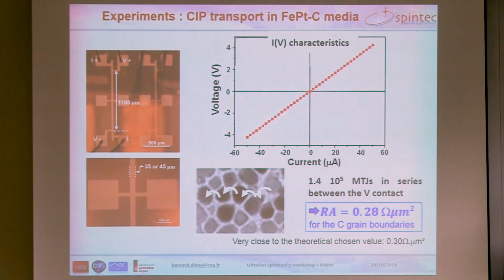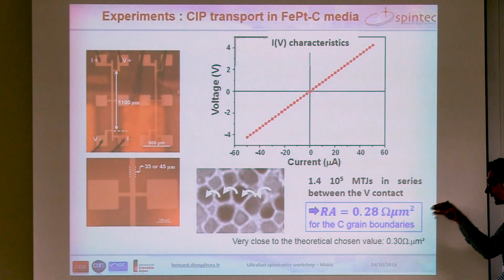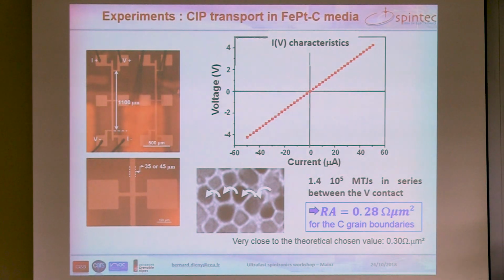And so in terms of electrical transport, the electrons are flowing in the plane of the recording layer. And basically, they are tunneling from one grain to the next through these carbon grain boundaries along the electrical field direction. So we can consider this recording medium as a number of tunnel junctions connected in series. And we have about 1.4 10 to exponent 5 magnetic tunnel junctions connected in series.